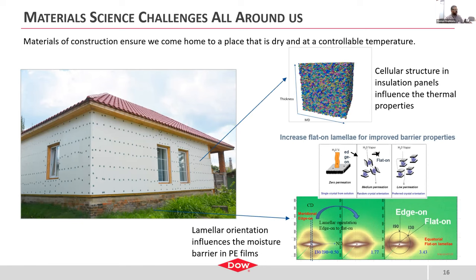Another area is around the high density polyethylene that is used as a moisture barrier in a lot of agricultural or foundation type applications around houses. Polyethylene is a pretty good moisture barrier. The way moisture propagates through a polyethylene film is it follows a tortuous pathway, trying to avoid the individual lamellar crystals and work its way through the material.